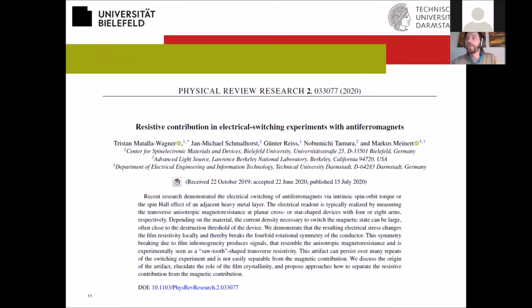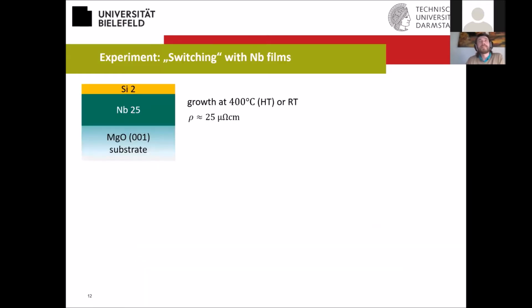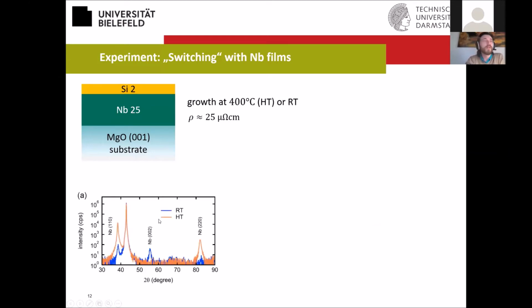So we decided to look into this phenomenon in more detail, and we looked at a system where we know there is no antiferromagnetic switching. As an example, we chose niobium films, which we've grown on magnesium oxide substrates. We've grown them either at 400 degrees C or at room temperature. So we have a high temperature sample and a room temperature sample. The high temperature sample is epitaxial, the other one is polycrystalline. This is what the XRD tells you. The high temperature sample has nicely 110 oriented growth of the niobium, whereas the room temperature sample has much smaller grains, as you can see here in the X-ray diffraction.